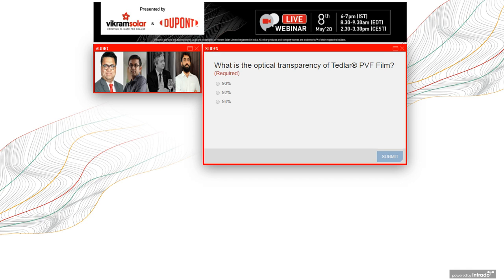Yeah, thank you. As I had pointed out in my presentation, these are two important considerations, obviously, because your modules have to withstand the UV of the sun, because you are in a light environment. So first up, we point towards the accelerated testing results, as Ivan also pointed out, and as internally I've shown that our backsheets go through, along with the testing that's done at PVEL. After us taking these through UV doses that would clearly match 30 years of field performance, 400 kilowatt-hour, we see very little degradation coming from UV. They have also, after going through the sequential tests at PVEL, which also combine a lot of UV, they don't show any signs of degradation.